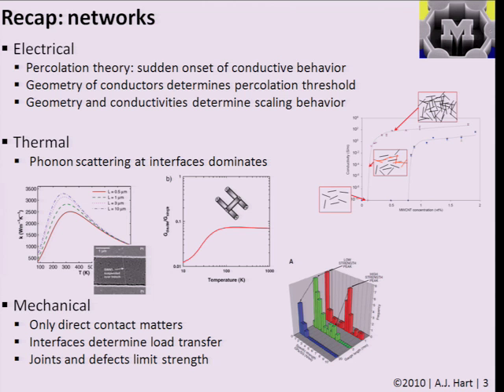To recap briefly: in the case of electrical properties, the electrical transport in a network exhibits a behavior called percolation, where you go from having no conductivity at a very low concentration of filler—nanowires or nanotubes—to a sharp transition in conductivity when you form the first connecting path across your film. The formation of the percolation network is geometrically determined based on the size, shape, and random position of the fillers. The conductivity value and scaling behavior depend on geometry, transport within individual nanotubes, their defect density and quality, as well as contact resistance between structures—based on direct contact or how the surrounding medium interacts, such as polymer or amorphous material in the gap.